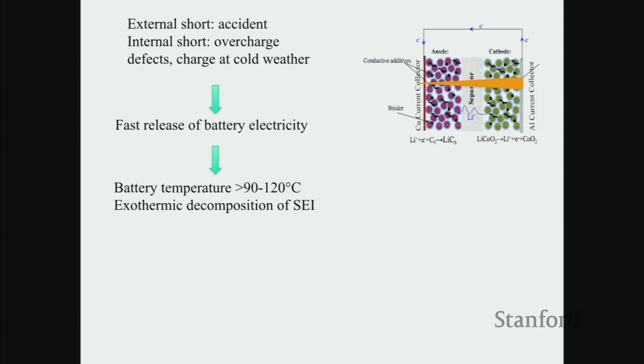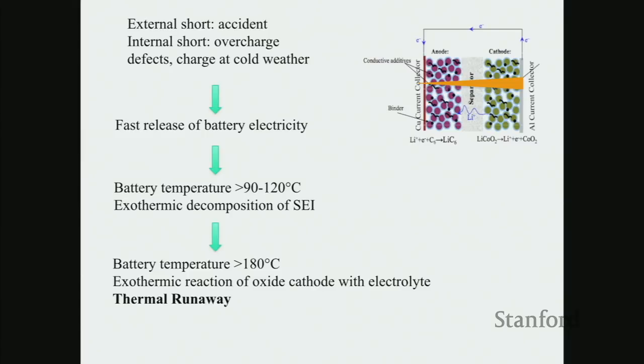The battery starts to heat up. At about 100 degrees C, roughly this range, the interfacial layer of your anode will start to have exothermic decomposition. That's why I was telling you SEI is quite important, this interfacial layer can affect your battery safety and your cycle life. And the temperature keeps going up because you are releasing more and more electricity. At about 180 degrees Celsius, an exothermic reaction between the cathode oxide and your electrolyte starts to happen. And this will quickly heat up your battery to 300 degrees C, 400 degrees C, 600 degrees C.